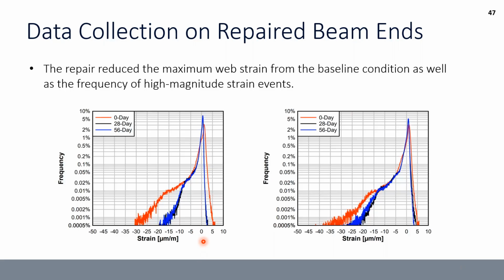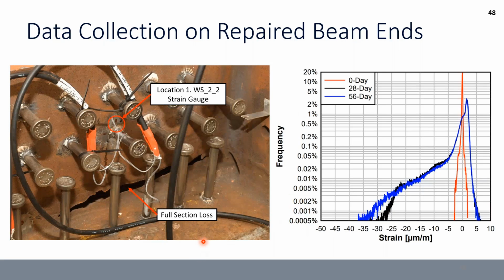But one of the really interesting trends that we saw is we did have one location on the bridge that had a full perforation, and it was over a foot long. In here, what we saw, if we're looking at the web strain, is that initially we were getting almost no strain because there was no continuous load path. And after repair, that location was actually picking up additional strain. So we were able to kind of really re-engage that portion of the beam end, which was great to see.